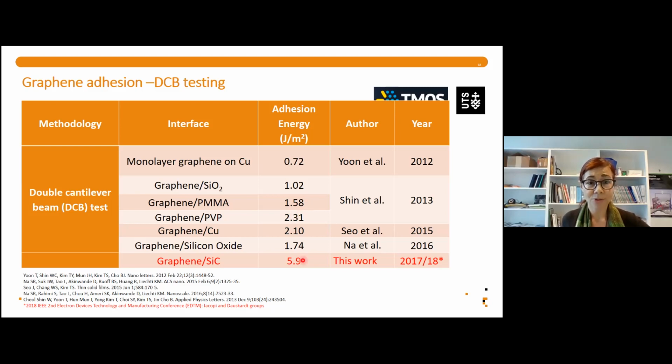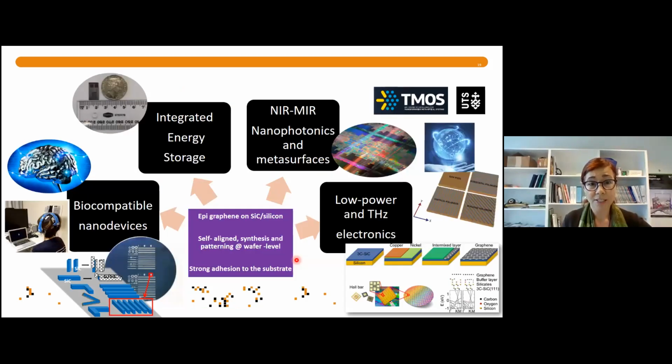We do have grain boundaries, and most probably around those grain boundaries there might be some oxidation bridges towards the substrate. However, those boundaries, in terms of sheet resistance, don't necessarily show up as a worse type of transport, not necessarily. But in terms of electrochemical applications, those boundaries are extremely important and extremely beneficial. And I hope I will have time enough to explain to you how.